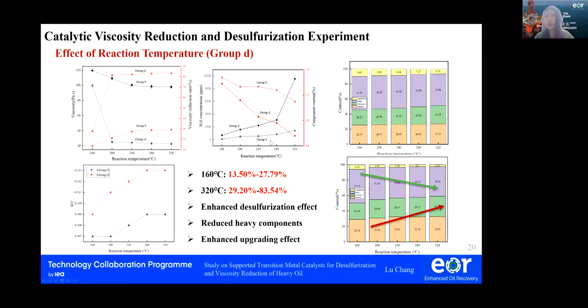The second figure shows the sulfur content of the oil sample after reaction at different temperatures. It can be found that the desulfurization effect increases with the increase of temperature. These two figures show the SARA contents of group B and group D. It can be found that the heavy oil components of the oil sample decrease significantly with the increase of temperature and the action of the catalyst. The last figure shows the hydrogen-carbon ratio in the oil sample after the reaction. It shows that the catalyst in group D can enhance the upgrading effect, and the effect is proportional to the temperature.